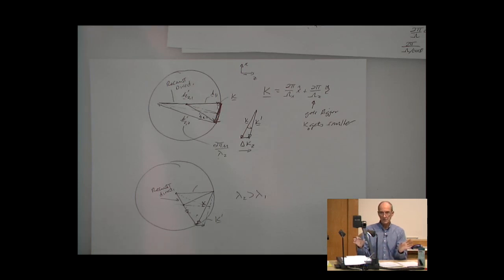And it shows up, so you can do the Bragg matching, illuminating with all wavelengths. One of those wavelengths matches, and it turns out that they are opposite depending upon which of the reconstruction directions you're looking at. So I thought that was kind of interesting. I never really appreciated that before we tried it, because I never forced the direction of reconstruction to be only one direction. But it's counterintuitive that you can get either a longer or shorter wavelength with the same change in the material.